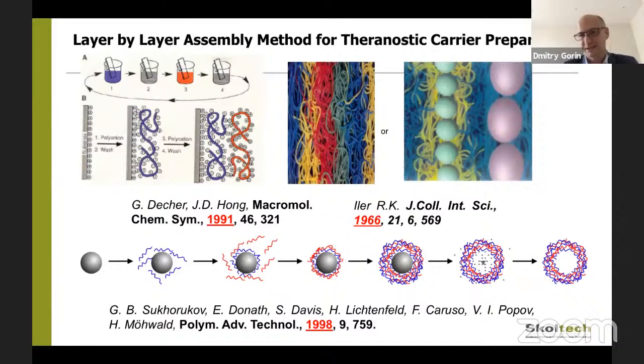And then how can we prepare such a type of object? We use one of the techniques named layer-by-layer assembly. This method was first suggested by Iler in 1966. And he used for preparation of such layers positively charged alumina, it's positively charged at neutral pH, and silica, it's negatively charged. He put a glass substrate first into alumina oxide, a water suspension of alumina oxide nanoparticles. And then after washing, he put the substrate into the silica colloid, and as a result, the negatively charged particles, through Coulomb interaction, interact with the previously positively charged particles and form the next layer.